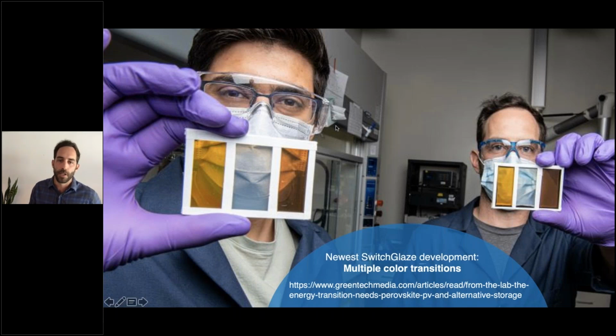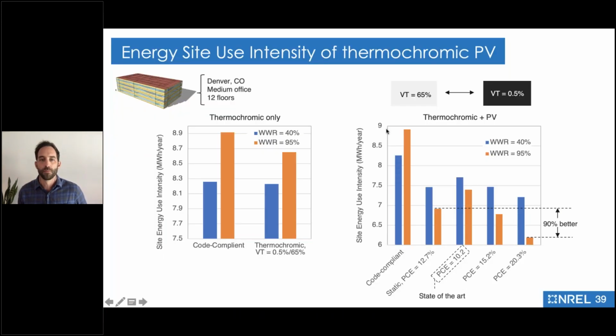So a recent development in this technology, this just happened, so expect a press release soon. This is actually from an article in GreenTechMedia. They got a little ahead of themselves, but on the left side here, this is my postdoc. He's a fantastic researcher. He's showing that we can actually make these perovskite materials go through multiple color transitions depending on temperature or how much of that vapor molecule you use. So the technology is progressing. We're getting tunability over the color, tunability over the switching temperature. That's why we're doing a lot of these studies, to tune the temperature of the switch and to improve the durability, which I will touch on before I finish.